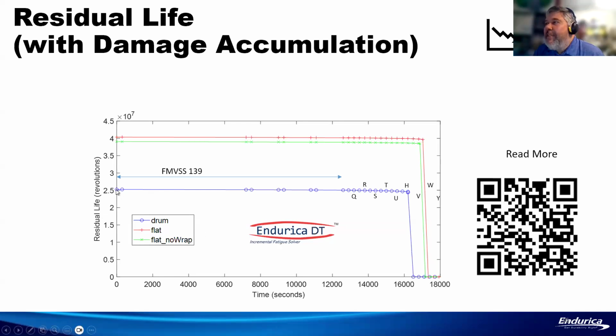So at time zero, before there's any history accumulated, there's a residual life on the tire. Let's say 2.5 times 10 to the 7 revolutions of the tire. Now, after the first load step of the test, if I accumulate those cycles and temperature field, you can see that the residual life does not change very much in the first 2 hours of the test.